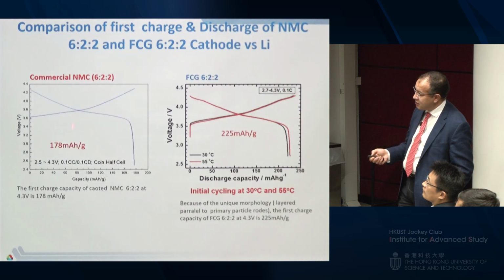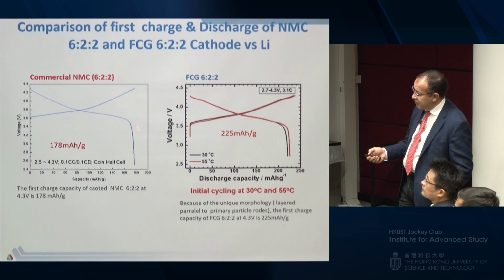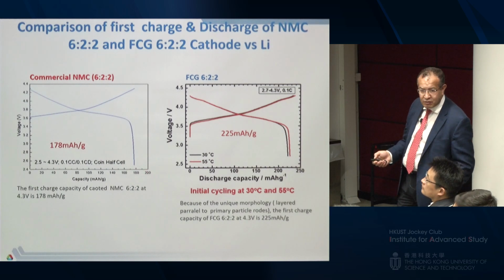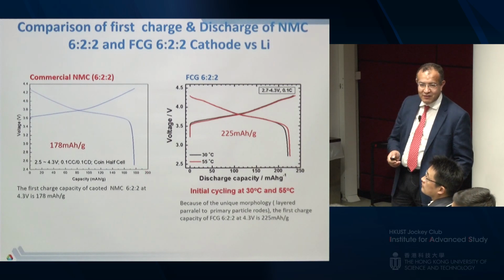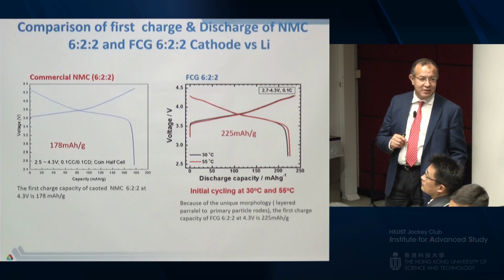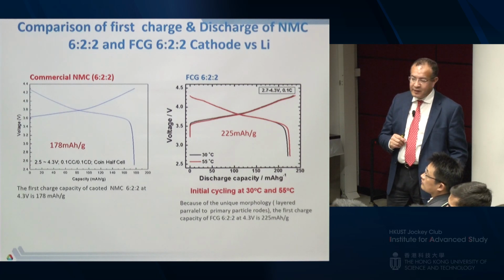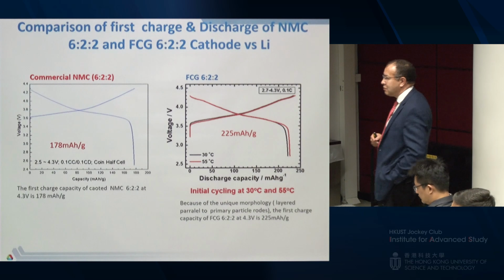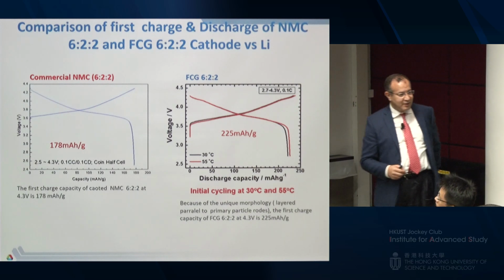This is the capacity using exactly the same condition. With the commercial NMC 622, we get about 178 at about 4.3 volt cutoff. Here we get about 225 because of that specific morphology, which is very critical. So morphology of material can also impact the performance of the material. Remember that.